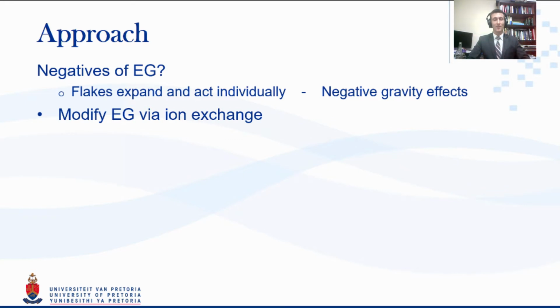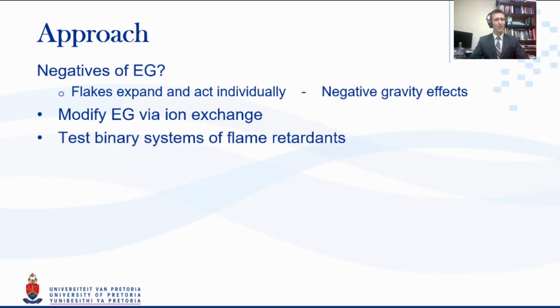One of the ions we identified was boron, which has a low glass transition. We surmised that if one could intercalate this through an ion exchange into the center of the graphitic structure, as it expands, it would become a sticky string that would stick to one another. Unfortunately, this was unsuccessful, but we had another card up our sleeves.